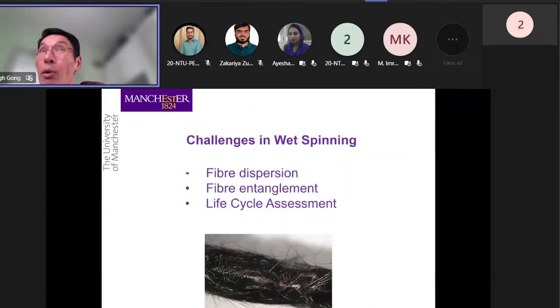So these are things that we have to further resolve. One is the dispersion of the fiber. The more evenly dispersed the fiber is, the better the eventual yarn, and that way you can reduce the entanglement. As we know in any spun yarns, any fiber entanglement is going to cause problems in the yarn structure. Ideally we want all the fibers in the yarn to be aligned in the twist direction, and that way we can control the strength of the yarn much better.